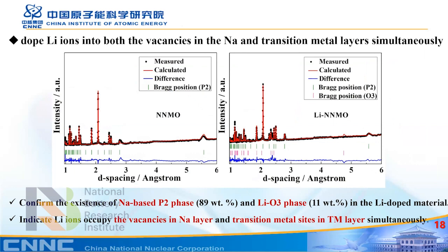So it can be found that two phases exist. The major phase is the sodium-based P2 phase, and the minor is the lithium-based O3 phase in the lithium-doped materials. The second conclusion: the lithium ions occupy the vacancies in the sodium layer and the TM site in the TM layer simultaneously in the P2 phase, as we expected.